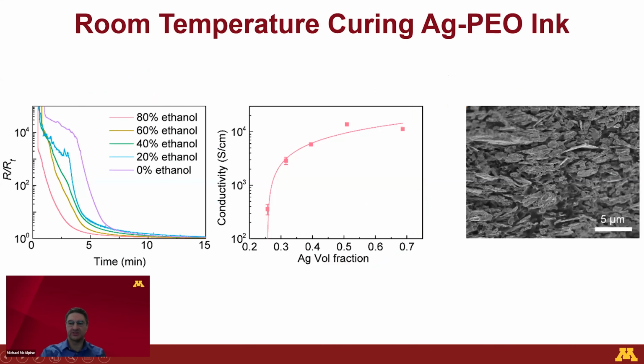So let's expand upon the ink a little bit. It's a silver ink again. It's in a polymer, and it's in an ethanol water solvent, and so it does actually dry within a few minutes at room temperature. And you can get basically within 2 orders of magnitude of bulk silver from this ink.